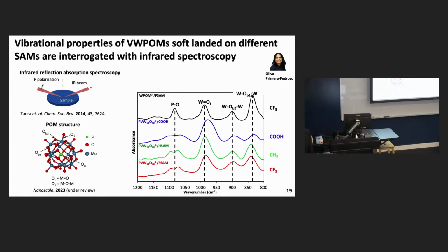What we were most interested in, though, with respect to qubits is how the vibrational modes change, because this tells you how the energy couples from the cluster to the surface and what effect that has on the decoherence rates. So to extract that information, we used infrared spectroscopy in a reflection absorption geometry as shown here. Again, the cluster has a structure something like this, where you have characteristic vibrational bands corresponding to terminal and bridging bonds. And the infrared results here are for the same vanadium-doped cluster soft landed onto 3 different monolayers, so CF3, CH3, and COOH terminated.